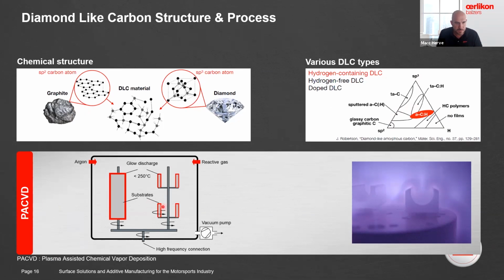Here, the coating will be made again under vacuum, but in a complete plasma environment. And it will then be done at a much lower temperature. So for sure, below 250 degrees C, we can even go down to 150 degrees to coat aluminum parts, for example.